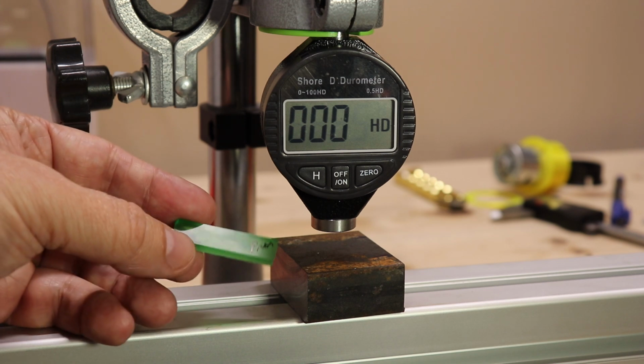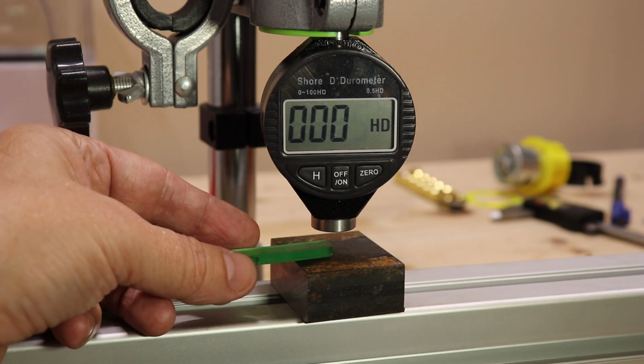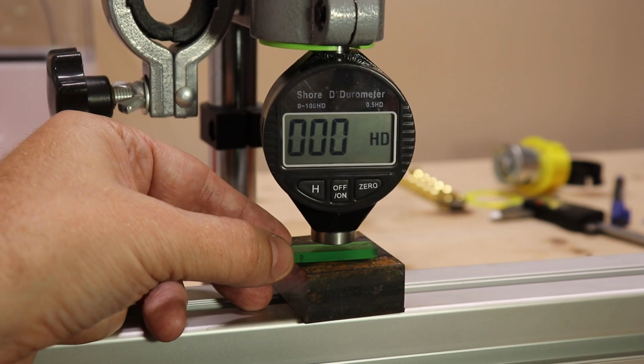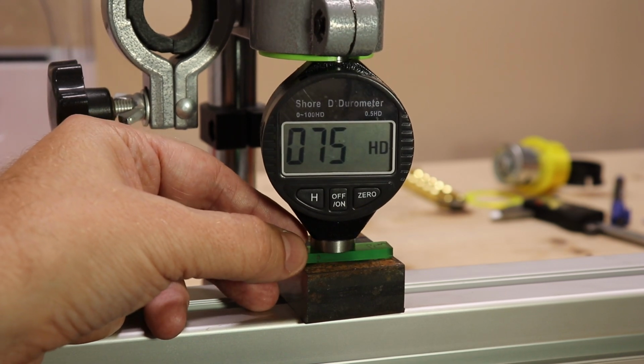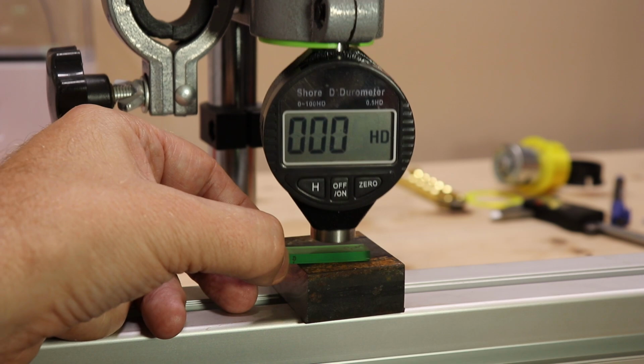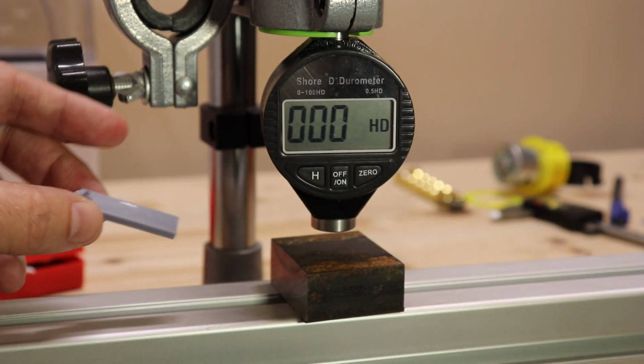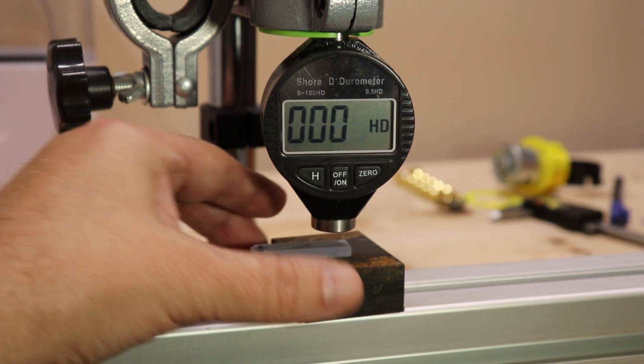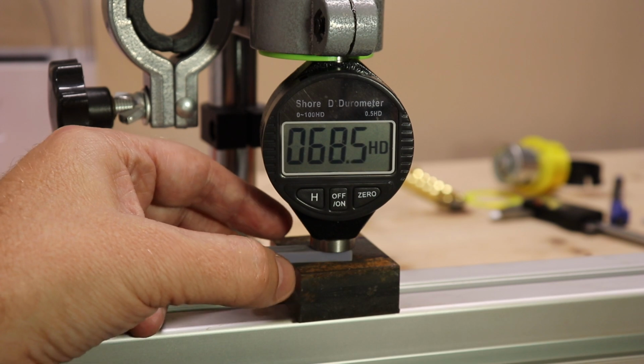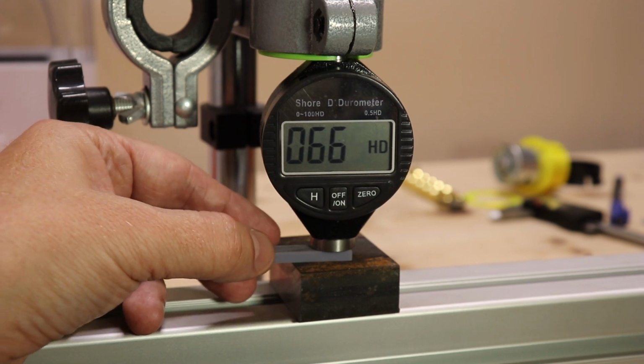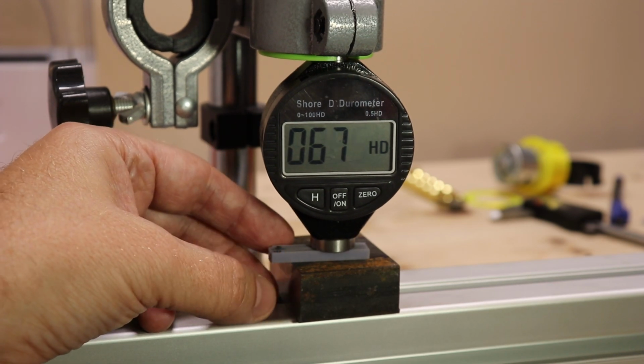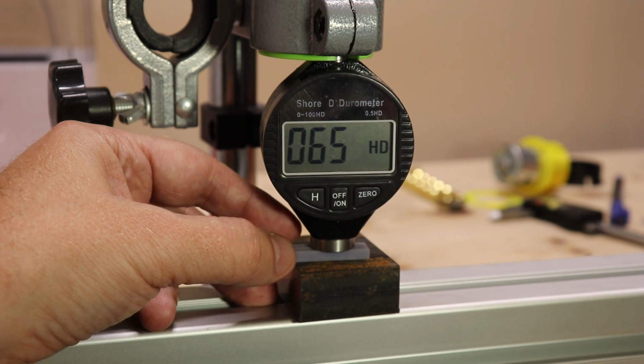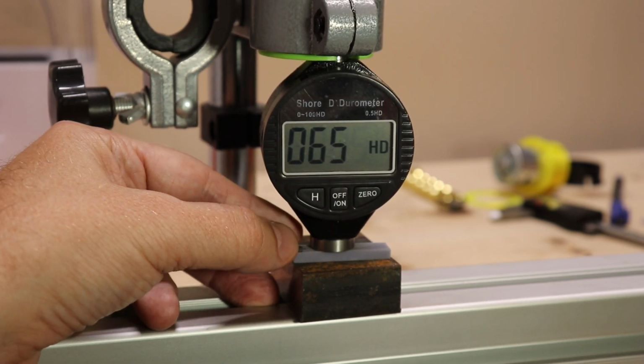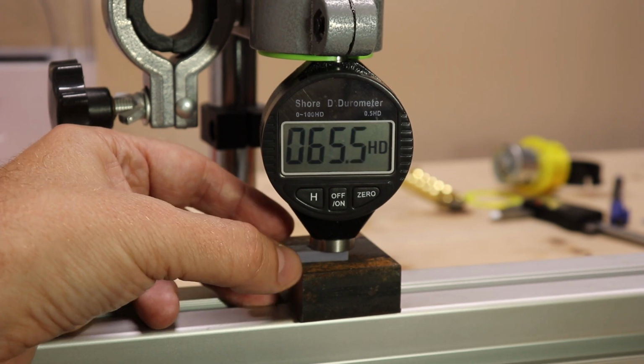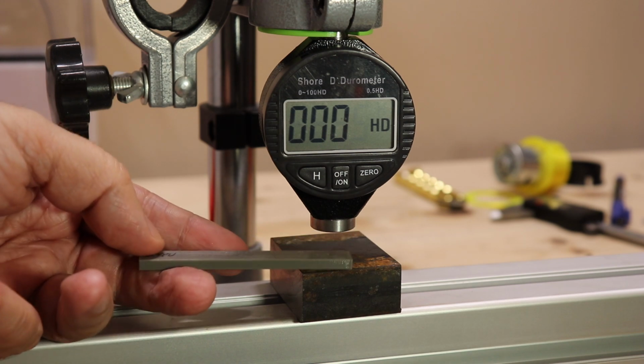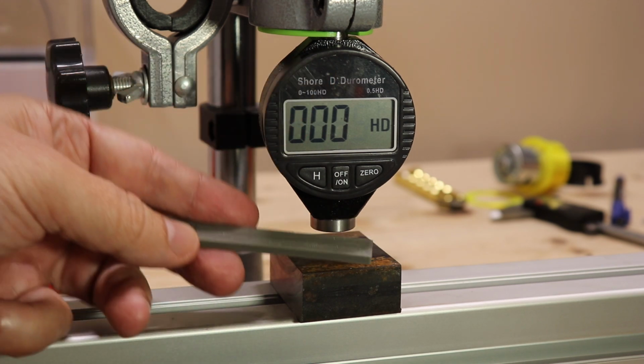And now let's measure some resin. This is Prusa Tough resin, also from one of my previous videos. 75.5, 75, 75, 75.5. And another resin, this is Elegoo water washable resin, also from my previous videos. 66, 66. I have to wait until the penetration ends. 65, 60, 65. And the last, 65.